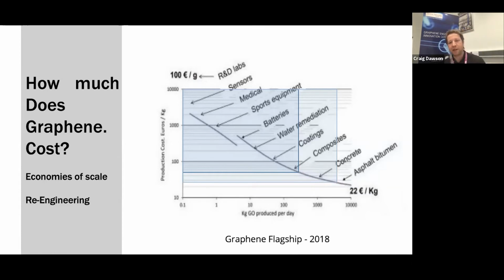This from the Graphene Flagship shows that maybe things like cement, concretes, bitumens and asphalts are potentially still too high at that price, but we're really seeing a move and economies of scale starting to kick in. And some of our suppliers and the supply chain are talking about $16, $20 a kilo. So that's really going to open up all those markets quite soon, I think.